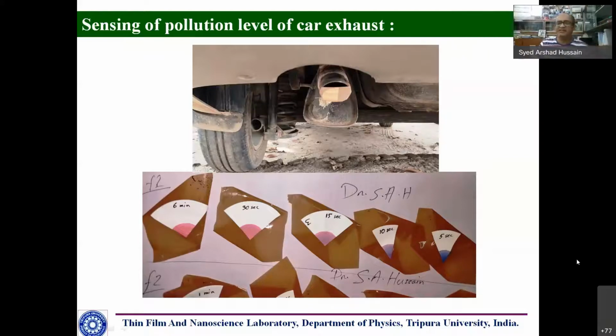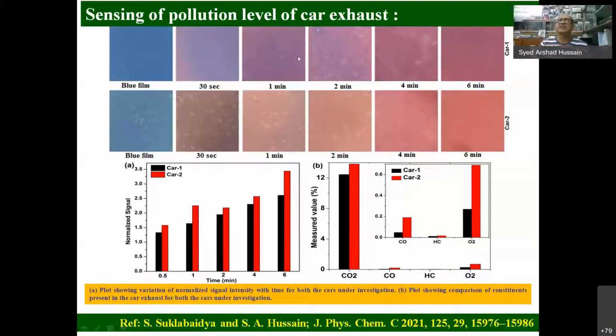We checked for several cars. This is a representative figure. You can see within 5 seconds the system started changing, and you see it's totally red phase. Then you can see some comparison of 2 cars. This is car 1 and car 2 at different times. We initially converted the PDA films into blue phase. Then we put the car silencer, and you can see after 30 seconds for the 2 cars, the extent of change is different.